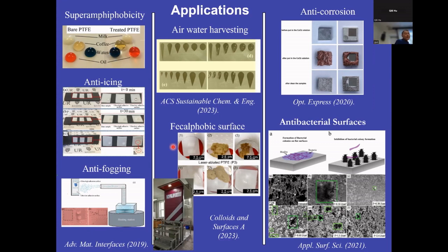Yep. Okay. So some obvious ones, right? So we did those, and then there's slightly less obvious ones. For instance, hydrophobic surfaces are antibacterial, and we demonstrated by trying to grow E. coli on a hydrophobic surface. We saw 99% suppression of the E. coli growth. Okay. And then we can even use this surface to harness water from thin air